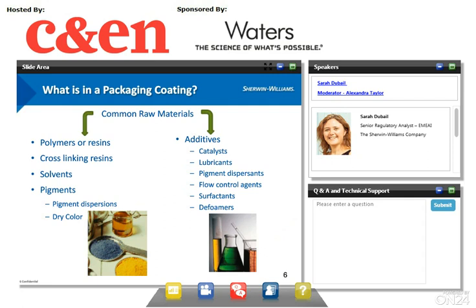The solvents are the carrier for the resins. They must be compatible with the resins, and they will influence viscosity and solids content, and ultimately application properties. The coatings are then cured, and the solvents will be removed from the final film. The coating can be functional or decorative, or both. Therefore, it can be clear, dyed, or pigmented. Pigments add color to the coatings — the most common one is TiO2.